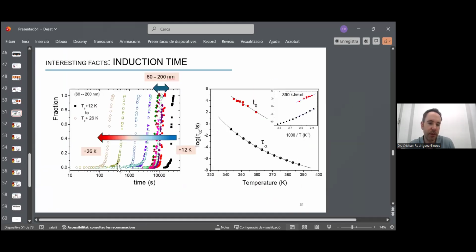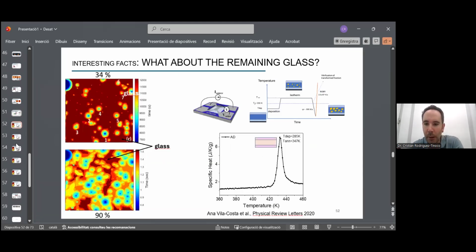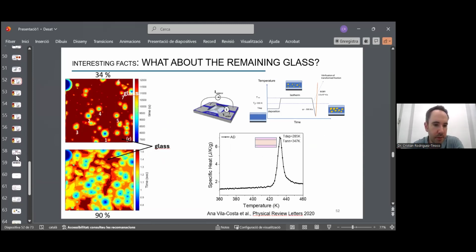This is about the induction time, the time we need to observe the emergence of this liquid, as a function of the annealing temperature, which has an activation energy which matches quite well the activation energy of the alpha process at this temperature, which means that this is a structural relaxation process. Okay, let me skip this part.